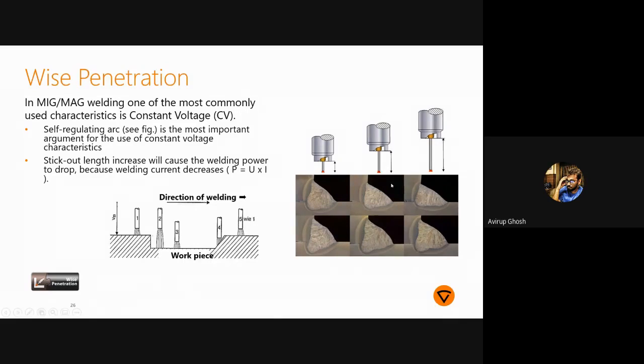So if you have, say for example, set around 250 amps in this region, it will go to around 180, 170 in this, when you have moved away around 10 mm from the original path. And another 10 mm shift will give you another reduction of around 30-40 amps current. And when you go on decreasing the current, the material that is going inside the weld becomes lesser, so the penetration is lesser.